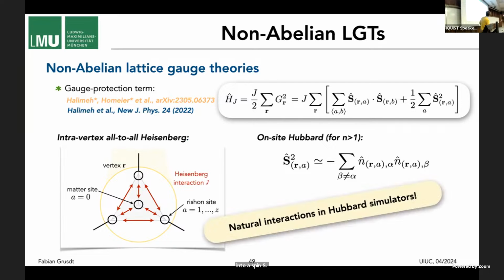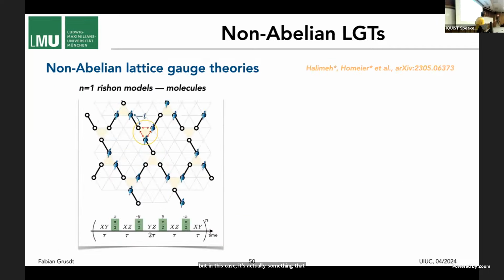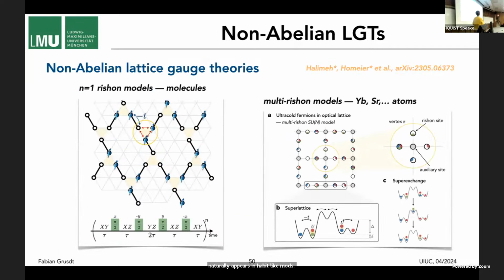And it turns out these terms in the Hamiltonian, the S.S spin interaction, that's exactly the antiferromagnetic interaction we needed for the Hubbard type physics. And this S squared interaction here, we can replace by an attractive Hubbard interaction. And so the upshot is, non-Abelian sounds harder, but in this case, it's actually something that naturally appears in Hubbard-like models. And this is, I think, a good promise for the future to use alkaline earth atoms to realize non-Abelian gauge theories too.